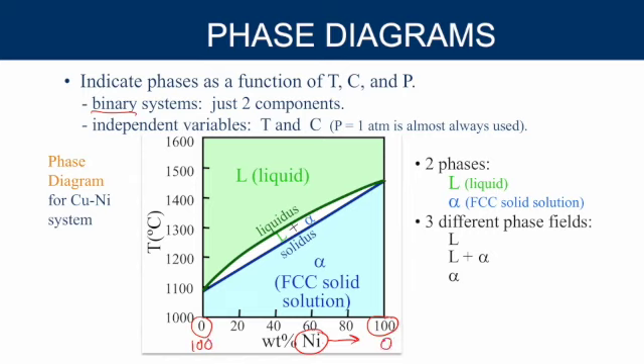If I just flip the numbers, 100% to 0, going in this direction, this would be the weight percent of copper, right? Because they always have to add up to 100. So if I have 80% nickel, I have 20% copper, 40% nickel, 60% copper. At any point, I always know the weight percent of the other component because they're binary and both components have to add up to 100.